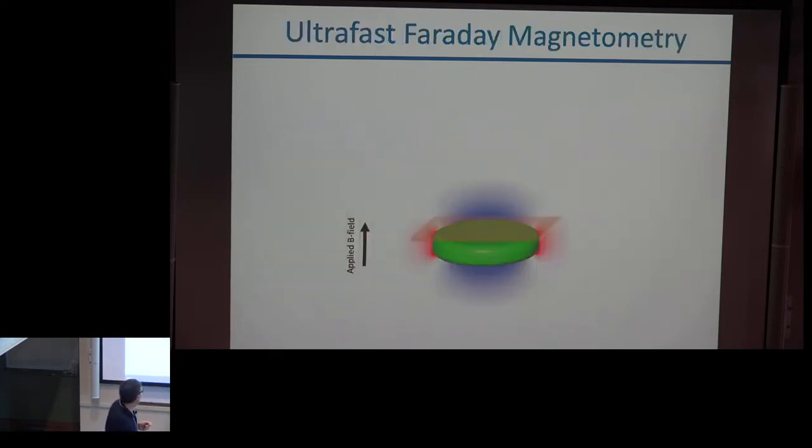So the way we did this is to take YBCO, and we slap a piece of a magneto-optic material on it, say either a garnet or anything that has a finite Faraday effect. We will be able to probe the magnetic field inside this external material, outside YBCO. So if we apply a field and we look at the polarization rotation of the reflected light pulse, we should be able to diagnose the density of the field lines immediately outside the sample. And potentially this can be done at very fast speeds because you can make this pulse very short. So that's basically the plan.